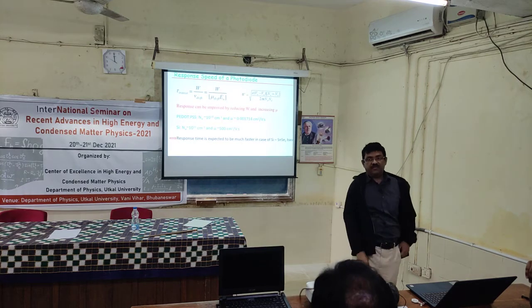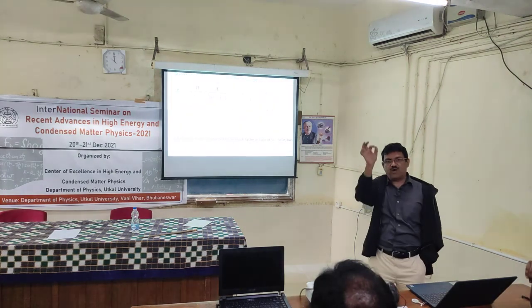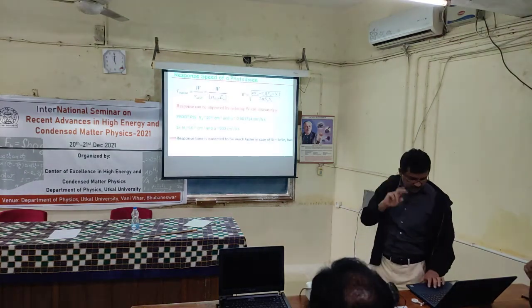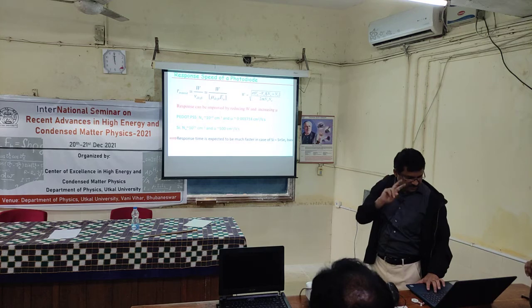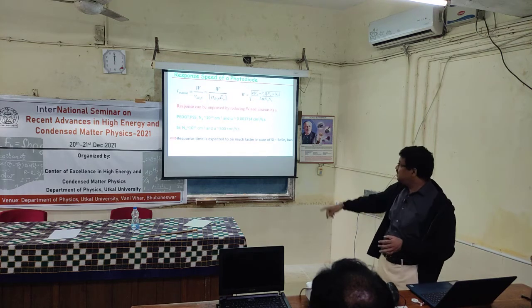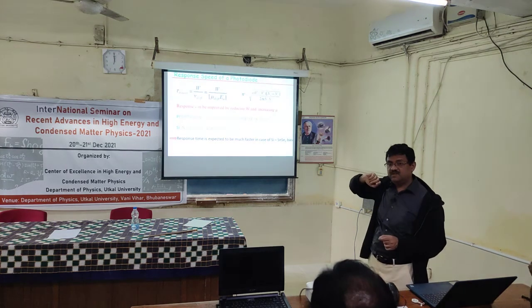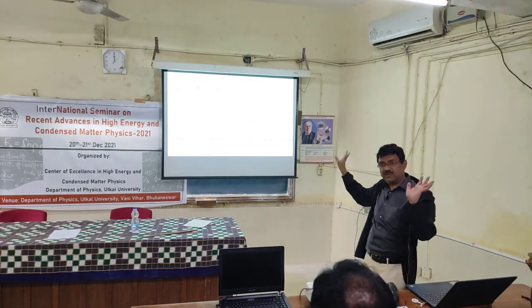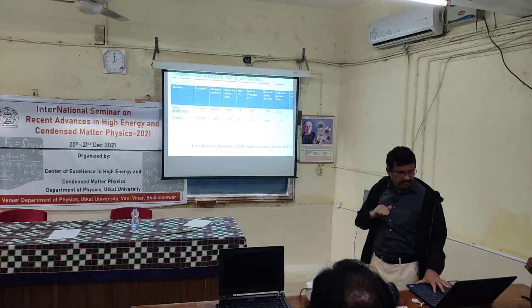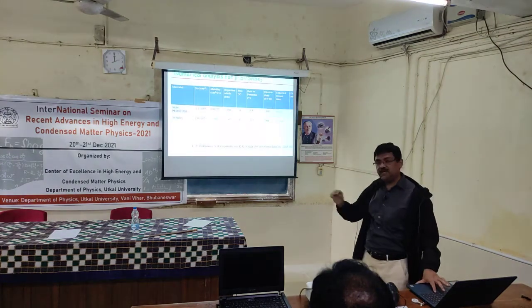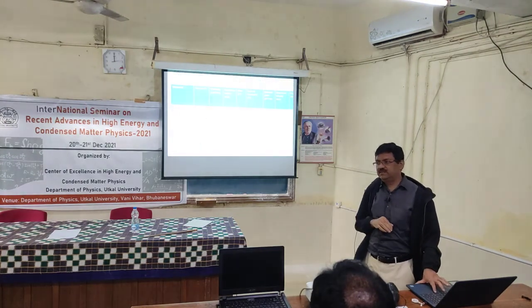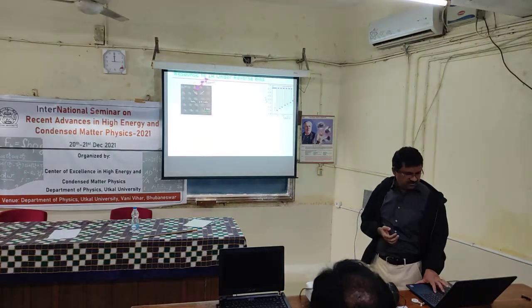And the response time is dependent on 1 by mu, if you remember the couple of slides we discussed in the beginning. So in that case, you see there's a huge difference in the mobility. So probably we can now go up to nanosecond or picosecond. So that's how we did. We deposited SnSe2 on silicon, and then we studied the time constant.